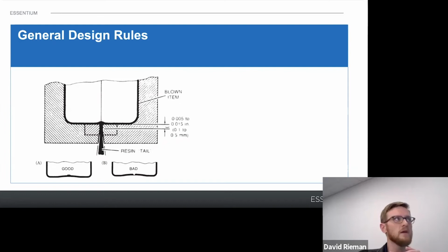And then typically a good size is about 5 thousandths to 15 thousandths of an inch, or 0.1 to 0.5 millimeters gap right there. And it's really important to try and keep those pinch offs designed very well. Otherwise you get a really bad pinch off, and you can see that on the bottom there at the right, where if you don't have that well-designed pinch off point, you're going to run into issues with part quality.